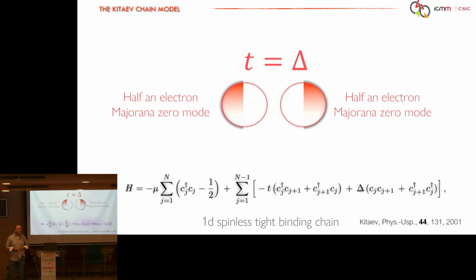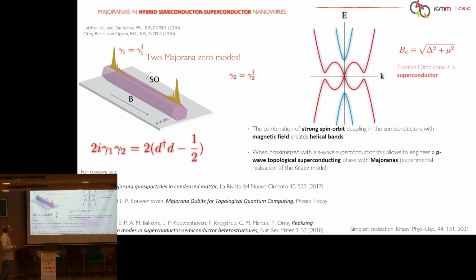This is kind of a toy model, but actually you can prove that there are more advanced models, like models of semiconductors with a strong spin-orbit coupling, that when coupled to superconductors, develop this kind of behavior at low energies. Essentially, the idea is that you can create, inside the gap of the superconductor, a kind of Dirac cone. Many of you have seen Dirac cones many times in graphene talks, in topological insulator talks. So you can tune a Dirac cone with electron-hole symmetry coming from the superconductor, and this Dirac cone can become topological and can host these Majorana zero modes.